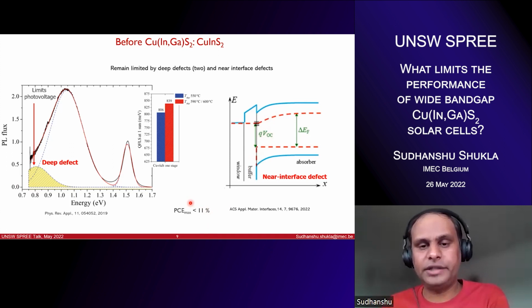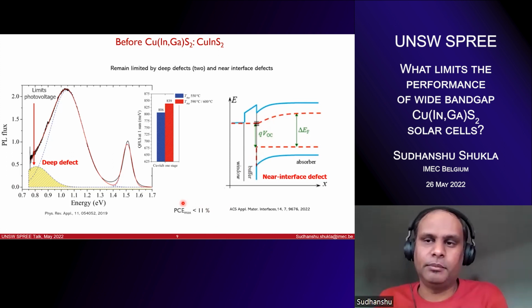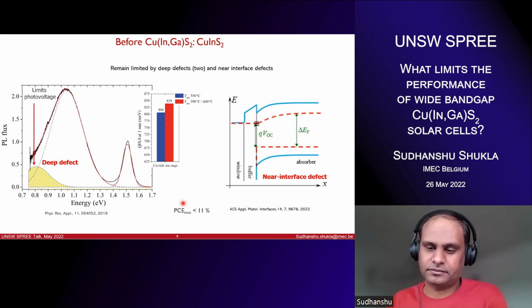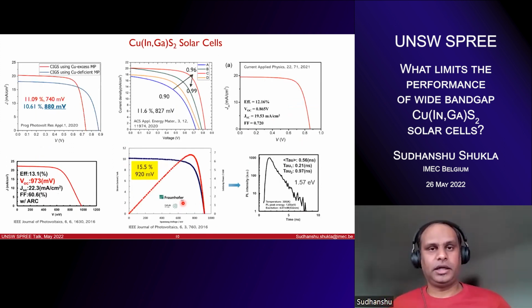And that has all led to the highest efficiency so far of only about 11 to 12%. So if you make CIS absorbers in your lab, most probably the numbers will be something like 8% to 9%. That's quite frustrating given the band gap of this material is 1.5 eV. Now you are looking at the CIGS solar cells.